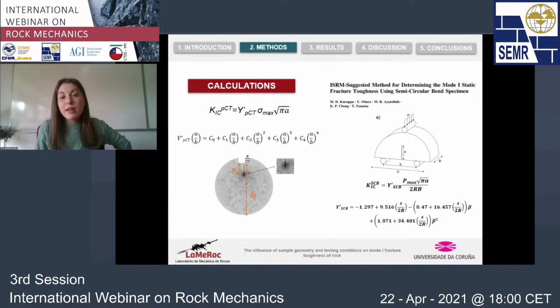To compute the fracture toughness for the SCB, we have used the expressions here on the right provided in the suggested method. And for the PCT, we have used the typical expression of mode 1 fracture toughness. And in this equation here, there are 3 parameters involved. The first one is this here, which is indicating the length of the notch. The second one is the maximum stress, the stress at the peak load, which is something that we know because we measure the load continuously during the experiments.